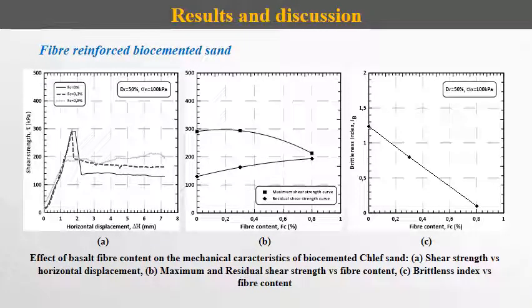The following figure presents the results of direct shear tests on fiber-reinforced biocemented Chlef sand at a relative density of 50% and different fiber contents. Laboratory results indicate a slight increase of maximum shear strength of biocemented samples at a fiber content of 0.3%, followed by an important decrease at a fiber content of 0.8%. However, all fiber-reinforced biocemented sand specimens exhibited more strength than natural sand samples.